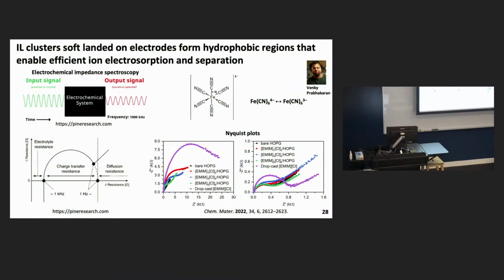So, in the case of separations, one of the key things we're concerned with is what's known as the charge transfer resistance, right? We have an electrode, we have ions that are coming to that electrode, and this is one of the key parameters that determines the efficiency of that process. So a technique we can use to measure that is known as electrochemical impedance spectroscopy. We use an input AC signal, and we measure essentially a phase-shifted AC signal as our signal or data points.